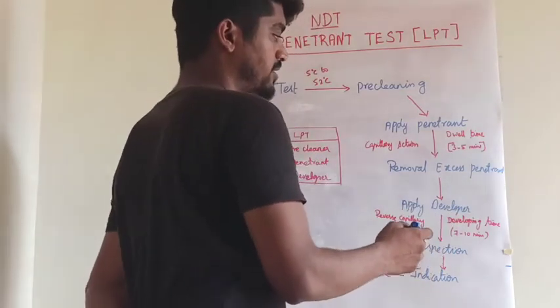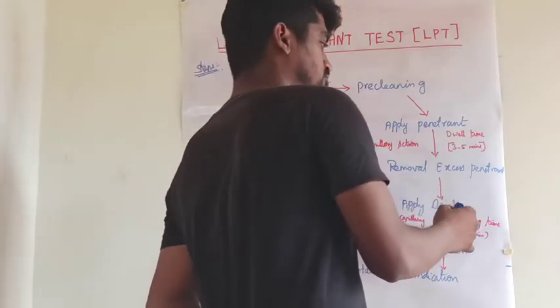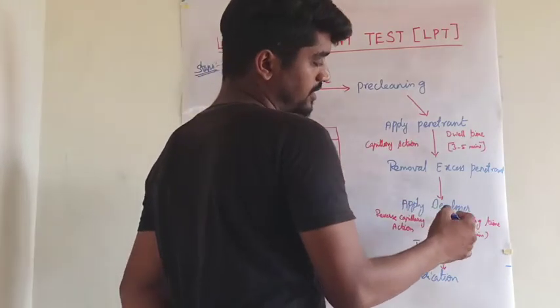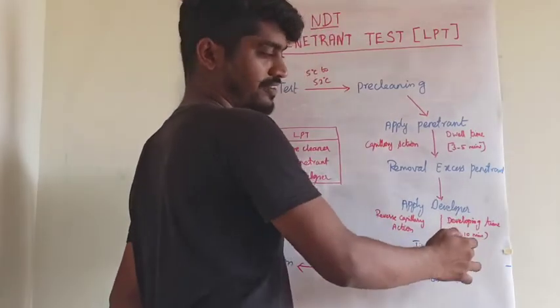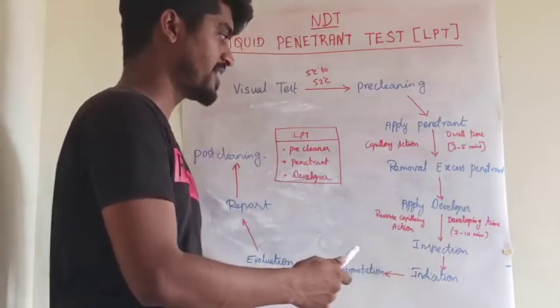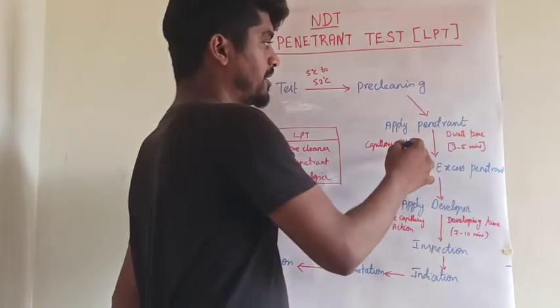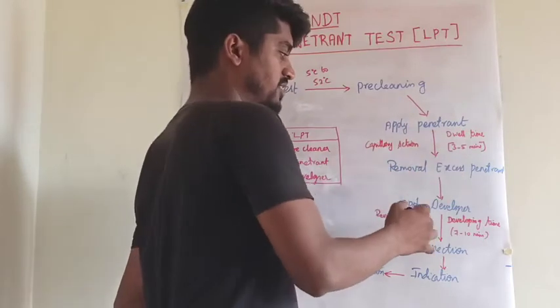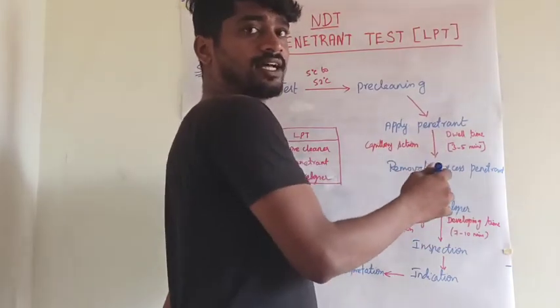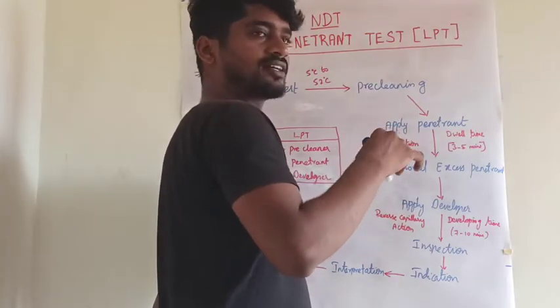Developers should be white or light colored to make defects easily visible. After applying the developer, it should rest for 7 to 10 minutes — this time is called the developing time. During that time, reverse capillary action takes place, pulling the penetrant back up into the developer. Since the developer color is white and the penetrant color is pink or red, defects can be identified as red marks on the white surface.